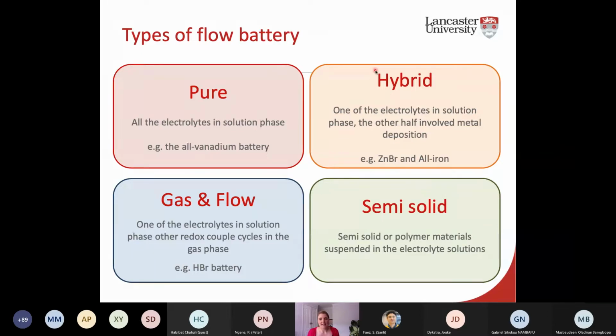The other leading system in this space is the hybrid redox flow battery, such as the zinc bromide battery, or the all iron flow battery, there's a few different ones. It involves metal deposition on one half of the battery. So that's where you have zinc being deposited on the negative side of the battery, such that the charge state is zinc metal and then a bromide complex on the positive side. And that means you've now moved from being a decoupled system to a coupled system, because your electrode is part of that battery system. So you're not going to have that advantage of a decoupled redox flow battery, but you do have the advantage of considerably lower cost electrolytes, possibly.